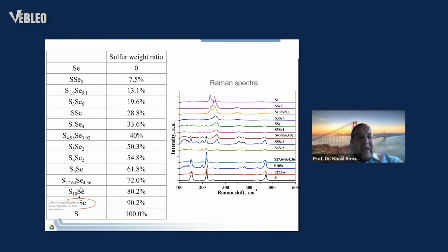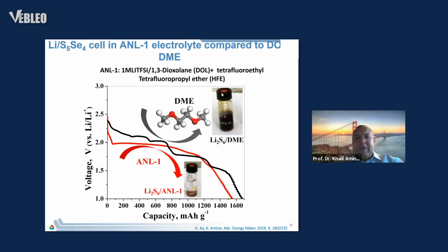These are not mechanical mixes. These are real phases that are forming. This is a Raman spectra of different phases that are totally different. So at Argonne, we developed a fluorinated electrolyte. We call it HFE, and used this material to see what happened. With sulfur in an ether base like DME, for instance, you have multiple steps that are an indication of polysulfide dissolution. With the new electrolyte, we have one step. We have one reduction peak that tells you that you move from sulfur to Li2S without this phase dissolving.